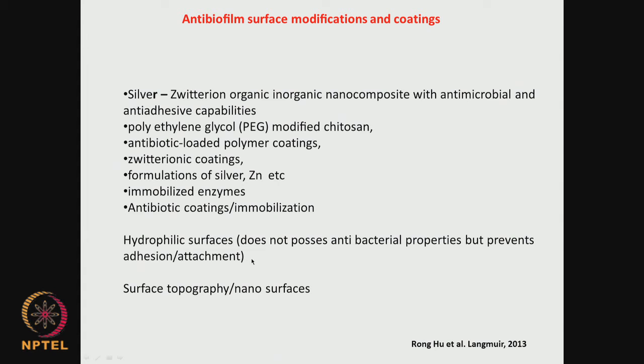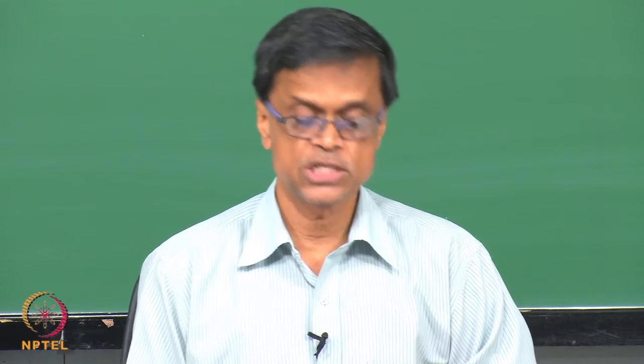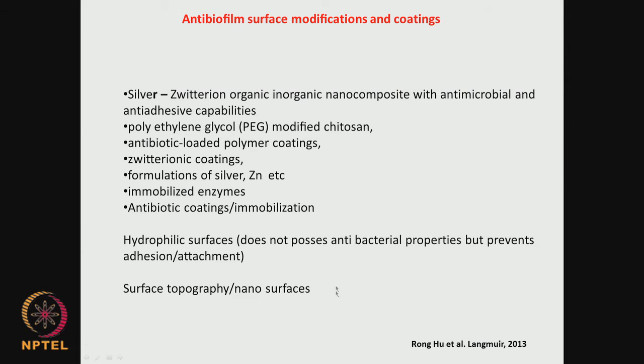Another approach is developing hydrophilic surfaces. Such surfaces may prevent the attachment of hydrophobic organisms, making them anti-adhesive. How do organisms acquire hydrophobicity or hydrophilicity on their surface? That depends upon the type of proteins present on the surface of these bacteria. There could be hydrophobic proteins which prevent attachment on hydrophilic surfaces, because the initial attachment is generally through non-bonded interactions like electrostatic, van der Waals, and hydrophobic interactions. Modifying the topography of the surface — creating indents or nanostructures — also prevents bacterial attachment.